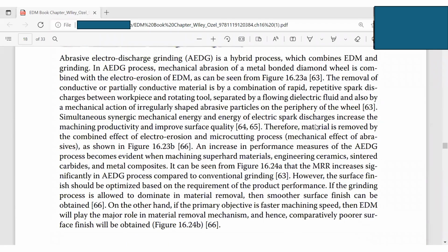So we can see the surface finish should be optimized based on the requirements of product performance. We just showed that if we increase the grinding, the surface finish is better. If we increase the EDM, the surface finish is worse. If the grinding process is allowed to dominate in material removal, a smoother surface finish can be obtained. On the other hand, if the primary objective is faster machining speed, then EDM will play the major role in the material removal mechanism, and hence a comparatively poor surface finish will be obtained.